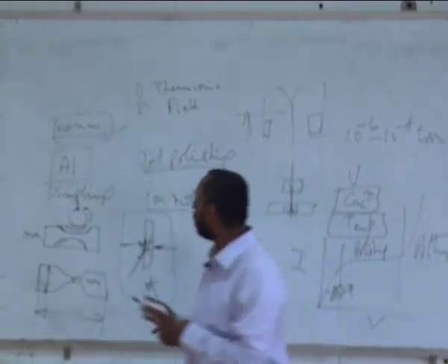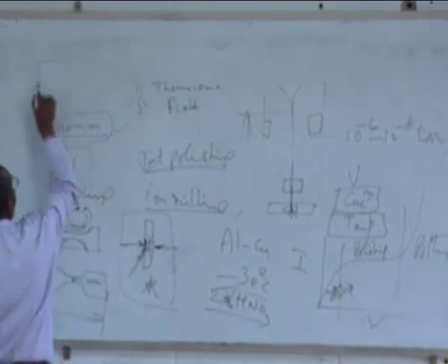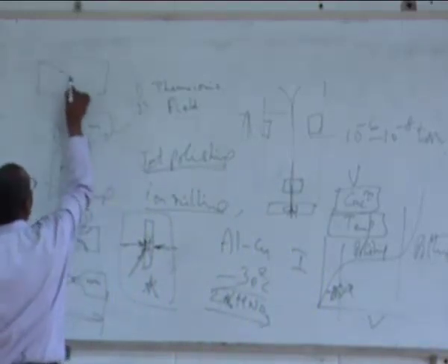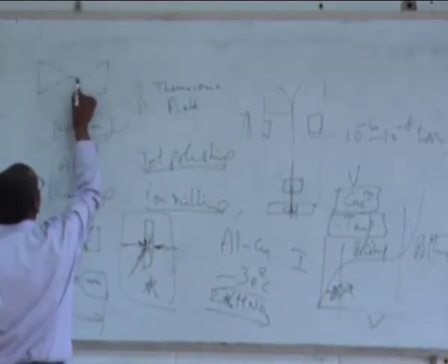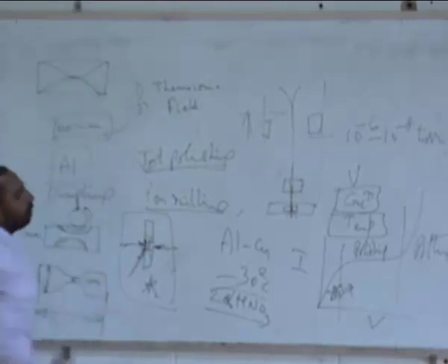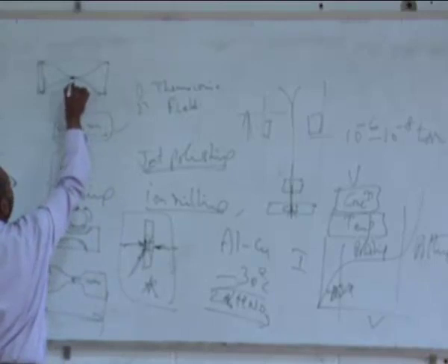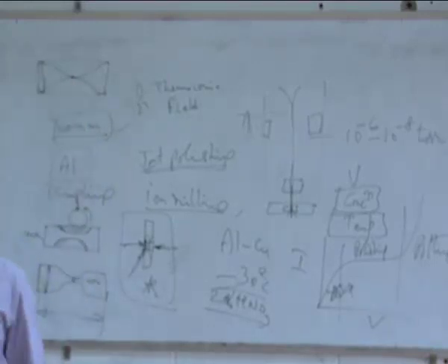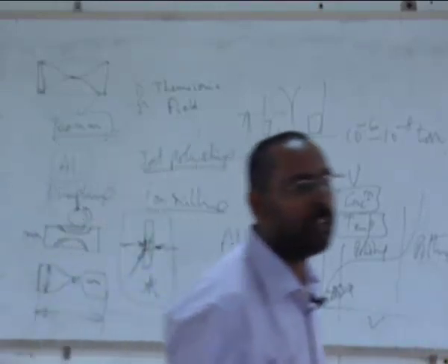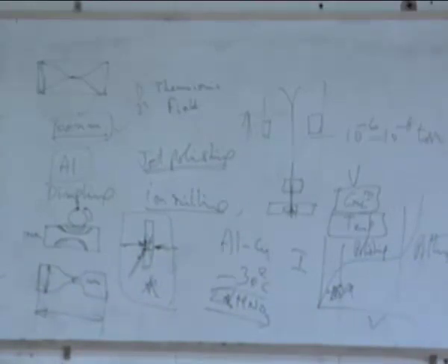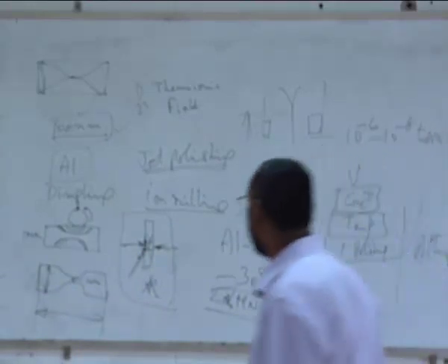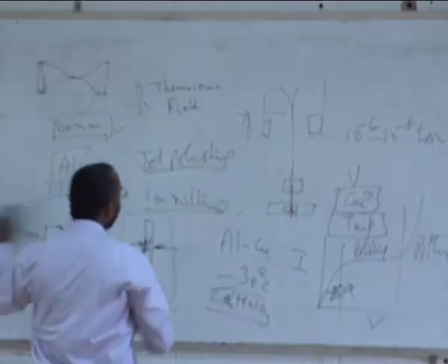So now in that 3 millimeter disc sample, which is a 100 micron sample, you see the center will be the one where the hole is formed. This is 100 microns, but here you will see a thickness which may be of the order of 100 nanometers. And similarly, how do I get such a disc in a ceramic sample? I cannot punch a ceramic sample. Ceramics are brittle. If I punch them, they will break into pieces. So there is a special technique again there, which we call ultrasonic disc cutting.